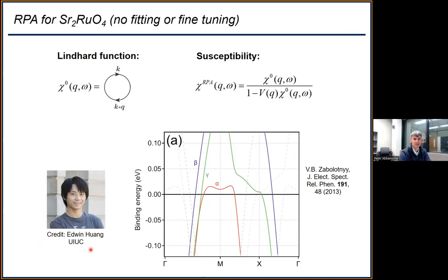And I won't get into a long diatribe on RPA. My experimentalist explanation is what you fundamentally compute in RPA is the Lindhard function. So this is the particle hole bubble. And in strontium ruthenate, we can do this more or less exactly, at least at small momentum, because the band structure is known. So the bands have been studied a lot with ARPES. There's a tight binding parameterization from Sergei Borisenko's group in Dresden that has really mapped this out nicely. So we just took the known band structure, plugged it into the Lindhard function and plugged that into the RPA formula. So there's no adjustable parameters.